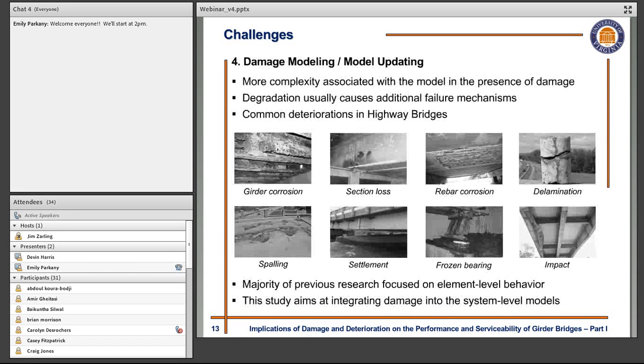The last piece of this modeling approach that for our particular project is actually very important is the damage modeling. The complexity of these models increases with the presence of damage being integrated, and the degradation usually causes additional failure mechanisms or premature failure mechanisms. Some of the common deterioration mechanisms in highway bridges, you're probably familiar with this if you studied anything with bridges: girder corrosion, section loss, rebar corrosion, whether it's internal to the deck or a pre-stressed concrete beam. We'll see delaminations in the deck, which potentially lead to spalling of the deck surface either on the top or the bottom. We could have global damage occurrences such as settlement, frozen bearings, or impact, or even fire.